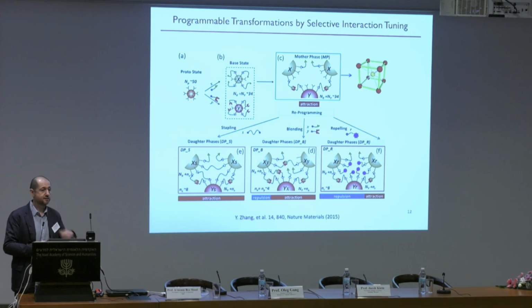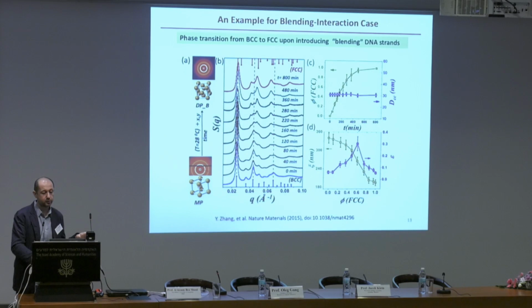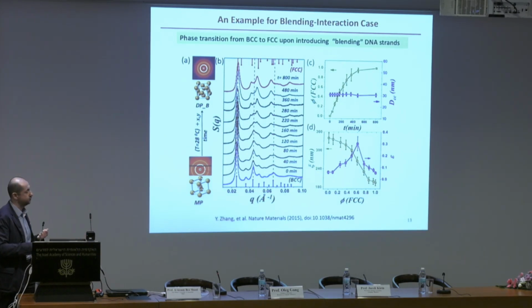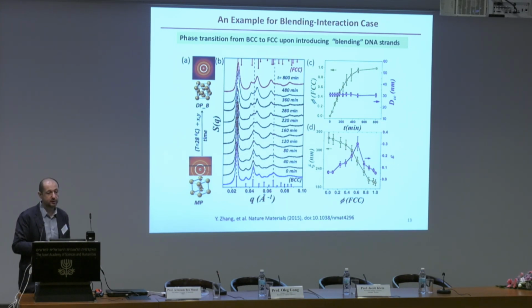So by doing something of this kind, we add DNA, and this allows us to observe the phase transition from one crystal to another. We can monitor this in situ using small angle scattering, starting here from this pattern, which corresponds to BCC. We add DNA strands, and we do nothing else, just wait and monitor. Over approximately 12 hours, you see the transition from one state to another. We can analyze that there is no intermediate state: BCC is dying, and FCC is appearing here. There are also all other types of characterization which can be done, essentially looking at the change in the correlation length during transitions and so on.